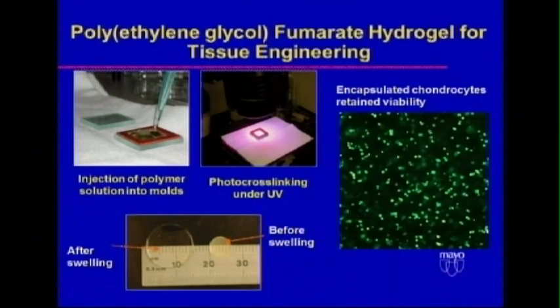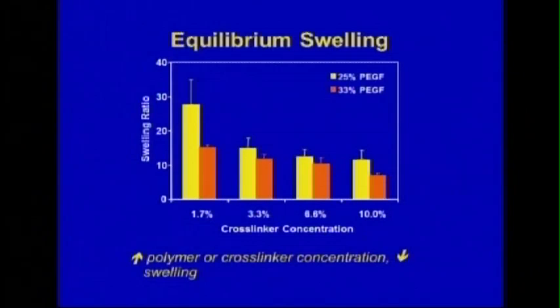And in the live-dead assay at the right, the cells live pretty well by diffusion because the hydrogel is well over 90% water, and wastes can get out and nutrients can get in pretty easily. And we can control the equilibrium swelling. It's, if you will, a spider web of polymer chains, and when they draw water in, they expand and expand and expand until the chains won't expand anymore. And we can control that amount of swelling, again, by the composition.